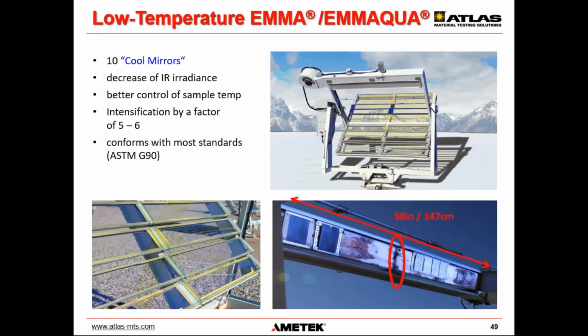Now, one of the more recent developments with this type of exposure is with some different types of mirrors, some that we call cool mirrors that I'll explain here in just a little bit. The standard EMMAQUA mirror has very good reflectance all the way down to that cut-on wavelength of natural sunlight, so that you basically also see the right shape of the spectrum using those mirrors. But that also means that you see all of that visible radiation as well as all of that infrared radiation that sometimes can make temperature a little bit of an issue. So with the use of these cool mirrors, we can decrease the amount of IR radiation to better control sample temperature and still give us that same UV exposure and UV acceleration as with the traditional EMMAQUA.